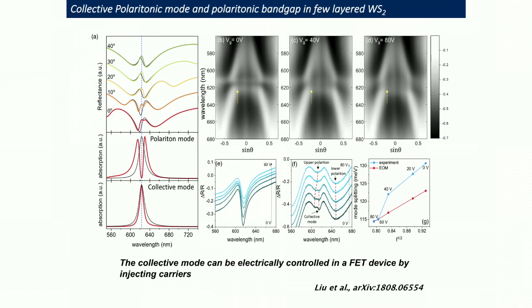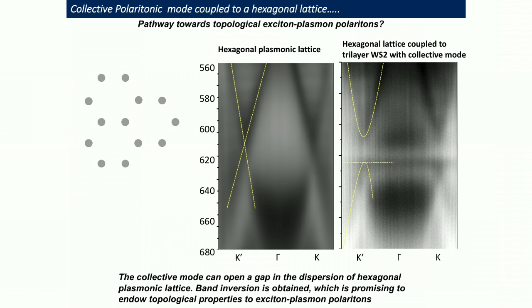And now because it's a collective behavior in the system, we are trying to do something more interesting, and that is by creating these more interesting lattices, like a honeycomb lattice, which can produce this Dirac dispersion. But then when we couple with this collective exciton mode, we can create this band gap in the system. And then we also have what is called inversion in the system. That means this band has properties of this band, and this band has properties of this band. So which basically means now there's hope that we can get topological polaritons in the system.